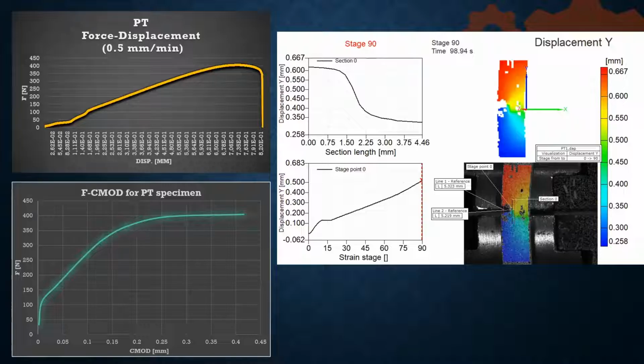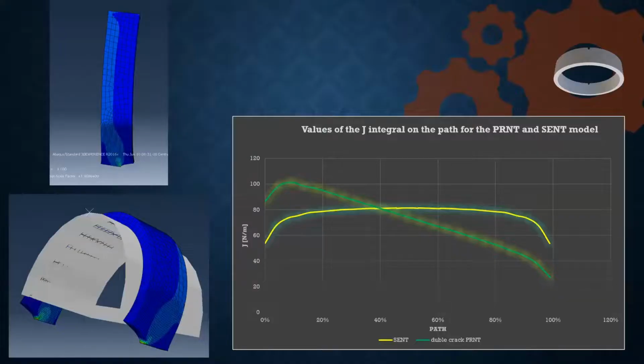And on all three displacement-strain stage diagrams, we could see a linear increase in displacement when it comes to the distances between the points. What is also important are the displacement area diagrams that are located along the color scale. In all three types of specimens, they indicated the regularity of crack growth.